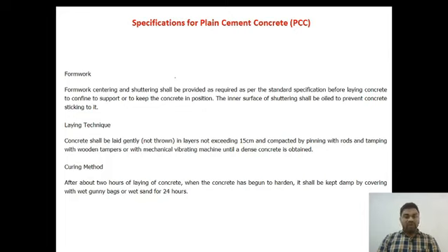Curing methods. After about 2 hours of laying of concrete, when the concrete has begun to harden, it shall be kept damp by covering with wet gunny bags or wet sand for 24 hours. As we know, the initial setting time of cement is 30 minutes and the final setting time of concrete is 6 to 10 hours. So after that, what do we need to do? We need to do curing about 2 hours after laying of concrete in hot areas. In cold areas, we can cure it after 6 to 7 hours, or even after 10 hours.